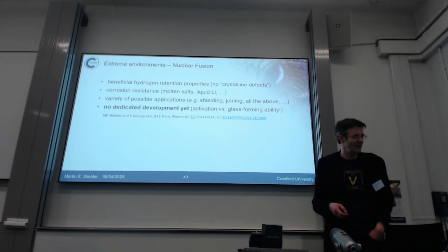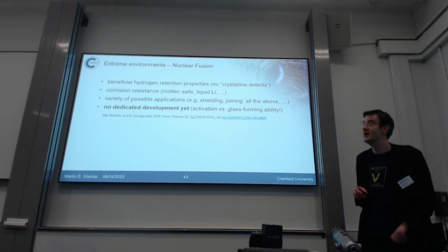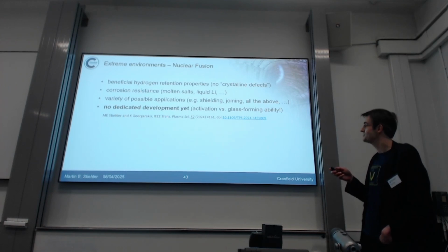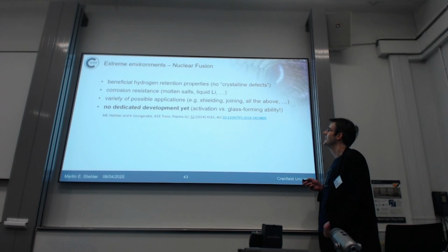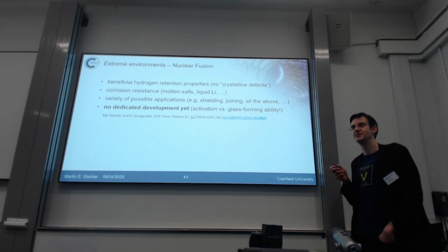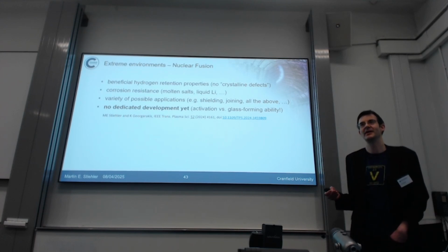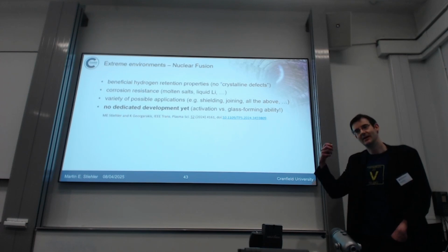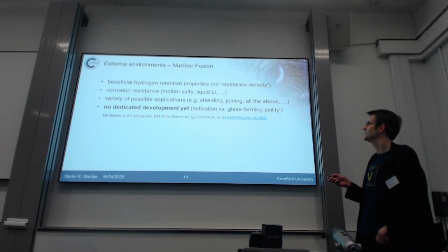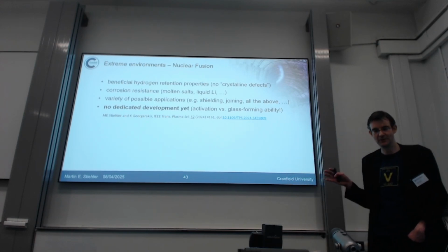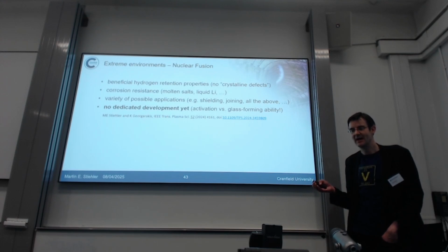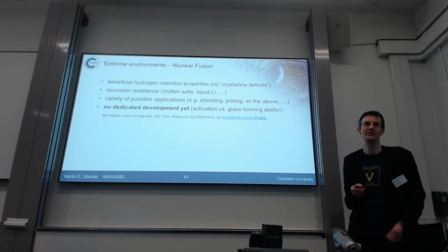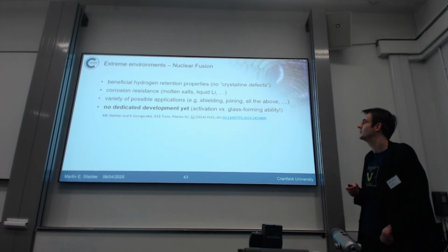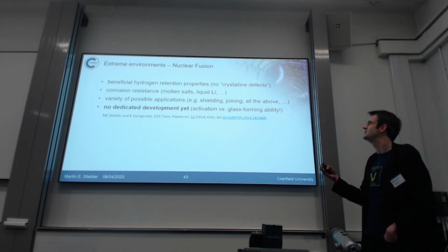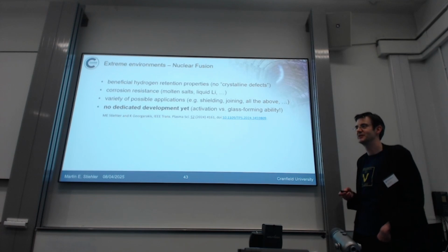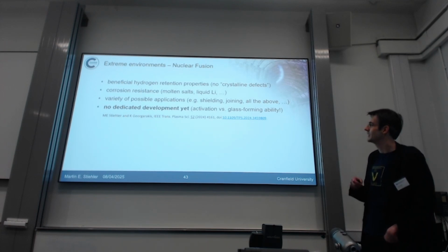And yes, there is a variety of possible applications you can think of, and as I mentioned, there's no dedicated development yet. One big aspect, and I think probably Thomas or James will talk about this in the afternoon, is something called activation. Neutrons can transmute elements in the material into radioactive elements, and you want to exclude these elements in your alloy composition. But sometimes this is a contradiction to the glass forming ability. I mentioned earlier that we have some empirical rules telling us which materials give a good glass forming ability, and the problem is that many of these elements are prone to transmutation into activated nuclides. So you probably need to restart your design thinking of metallic glasses from scratch and see what elements are possible and how we can still get high glass forming ability.